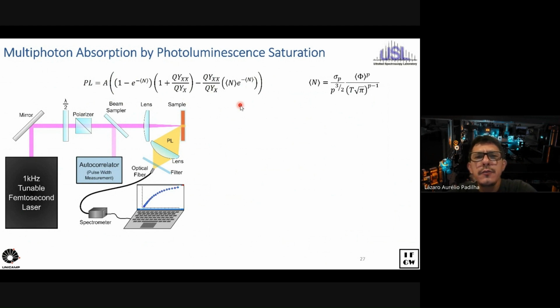And if you fit this, you get the average number of excitons for each pump intensity, and basically you can correlate the average number of excitons to the photon flux and pulse width of your laser and the absorption cross section. The pulse width of your laser and the photon flux you can easily measure. So you only have to measure the power of your laser and the spot size at the sample, and here the pulse width.